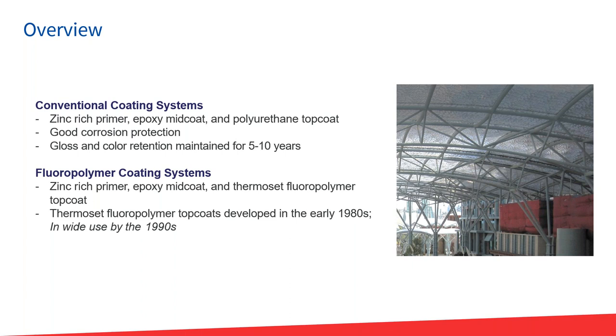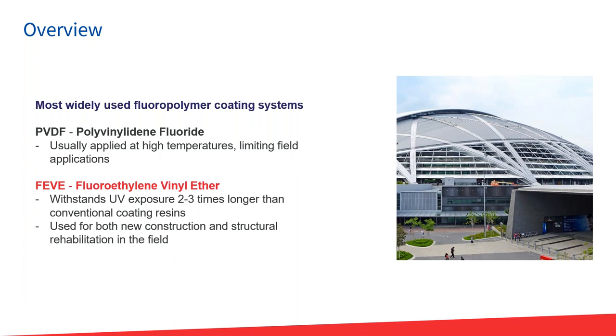And you'll see a term here that I'll explain quickly, thermoset. It's important to use this term and clarify, because there are other fluoropolymers in the market, which we'll get to in a moment. Most of the time in a top coat system using FEVE, you're cross-linking the system, much like you would a polyurethane or even a polysiloxane. And so those systems that are what we call cross-linked, they're basically hardened, and we call those thermoset. So that's kind of the terminology there. And these thermoset fluoropolymer systems were introduced in the 80s and became widely used by the 1990s.